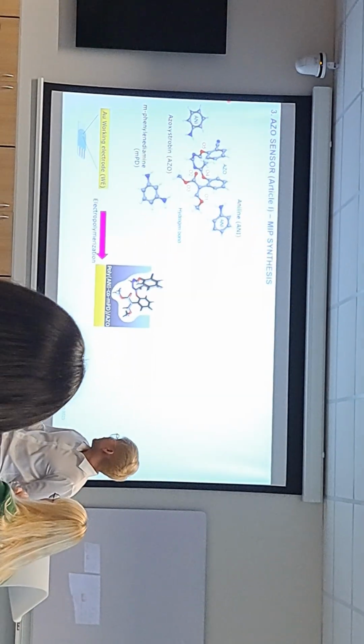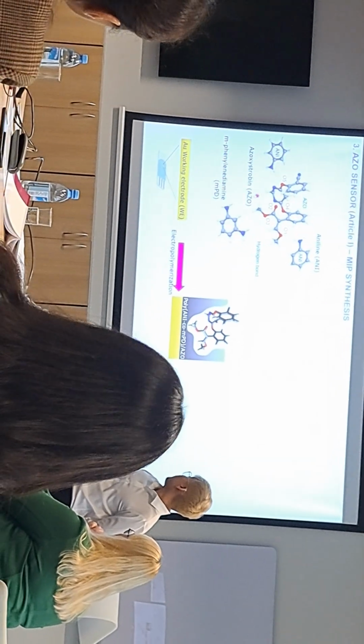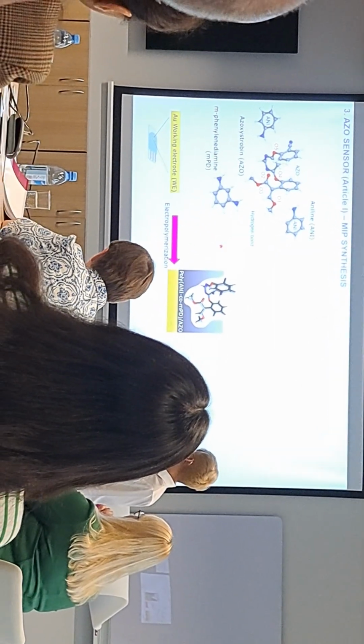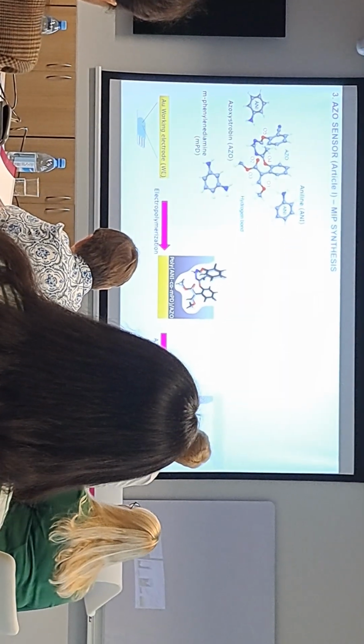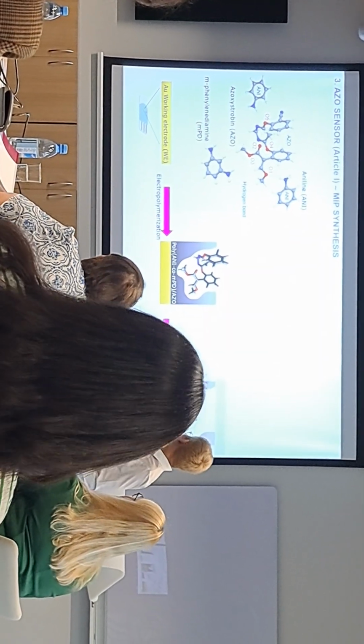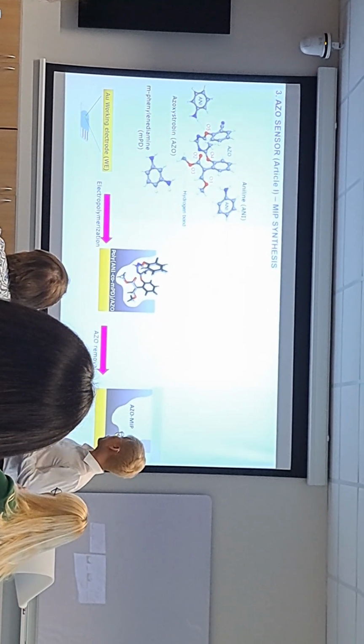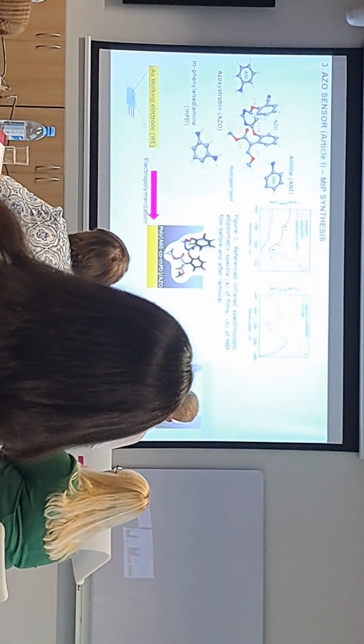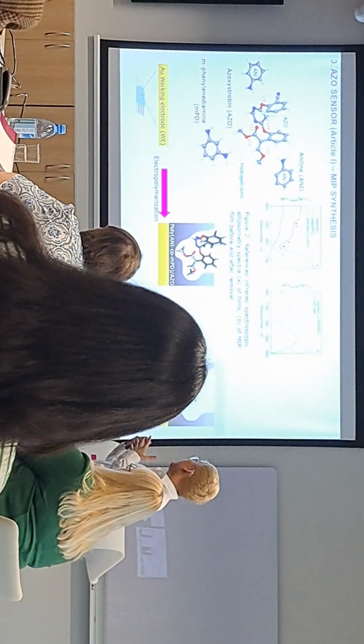I put inside the energy enough to oxidize and form the polymer from all the monomers. However, the energy is not enough to change the template into something else. It continues to be held here by all the hydrogen bonds surrounding. Because it's weak, it's easy to break those bonds and leave behind the material with the cavity specific for azoxystrobin. And this is the result of characterization using infrared spectroscopic ellipsometry.